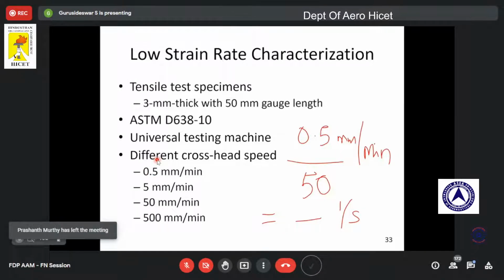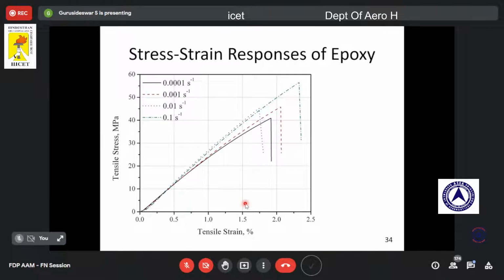We chose four different cross speeds: 0.5 mm per minute, 5, 50, 500. Generally we test at 5 mm per minute for quasi-static loading to understand the mechanical properties. But here we have tested at different velocities to understand the behavior of the material at different strain rates. So this is the response. One can see the difference in stress and strain at different strain rates. 0.0001 corresponds to the lowest strain rate.